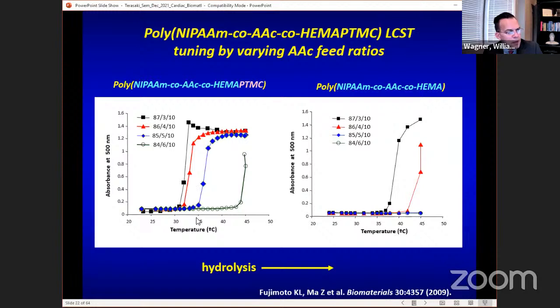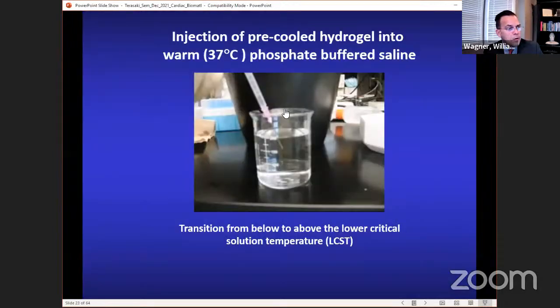So the point is, body temperature at 37, this one is not relevant because it does not go through the phase change until way above body temperature. So that one's out. These three are possibilities. They all will gel in the body. And now after we've cleaved this off, we want them to be on the other side. So these two, the red and blue, are candidates for being used because they do exactly what we want. They gel, and then when they degrade, they will diffuse away. So that's basically the material design, or one aspect of material design.